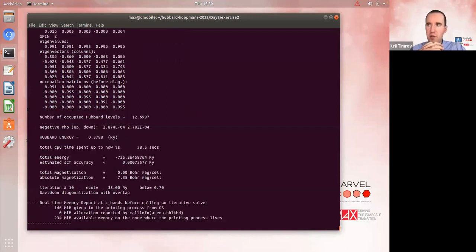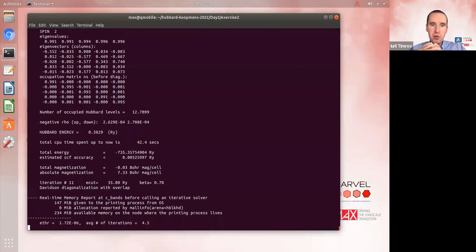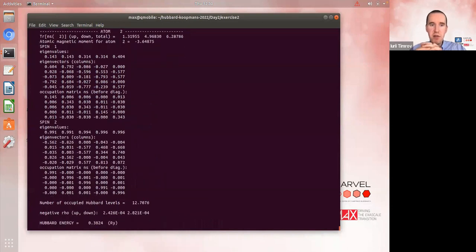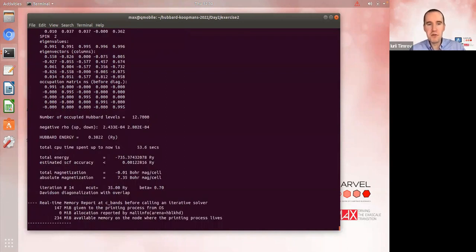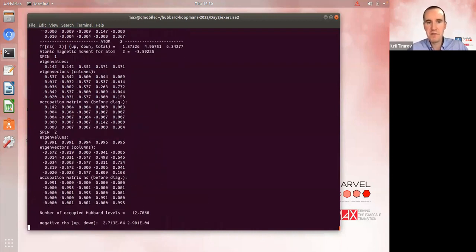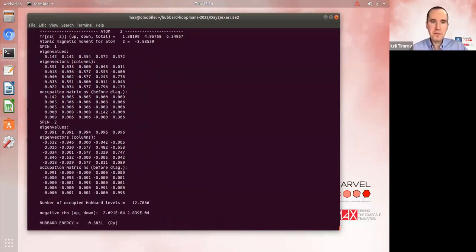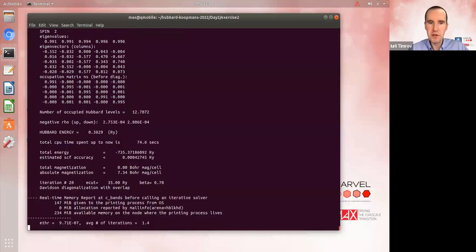In this case, it is the SCF one, because the K mesh is coarse. But if you use a dense enough K mesh, both Fermi energies should coincide. So it doesn't really matter if you take it from SCF or NSCF, because it is the same. In this case, they don't, because it's not converged, because we don't have time to run very expensive calculations. But for demonstration purposes, it's enough. It's not really a big deal if it's not converged. It's already sufficient for us to discuss what we want to discuss. But when you want to publish results, you really need to perform careful convergence tests.